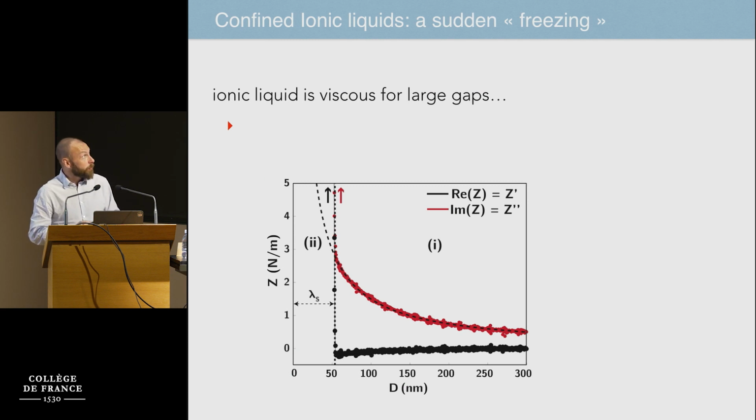So that was the experiment. What we show here was very simple; the idea, in principle, was simple. We start to confine. So what is happening when you approach the probe, the tip, to the sample? When you're quite far, you basically recover a very simple viscous behavior with a dissipation that is increasing following the Reynolds force. And this goes quite well for confinement down to a few hundreds of nanometers. And the stiffness stays almost zero. At that time, we considered this to be zero.